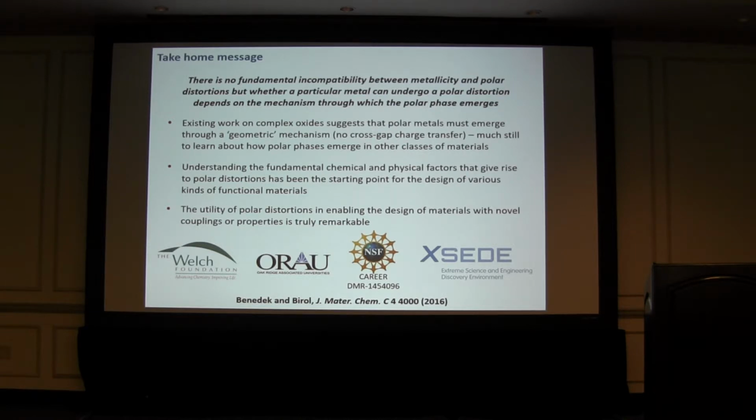I'm not convinced about your insistence on the fact that the Born effective charges contribute to the force constant, because they contribute only for longitudinal phonons, and here in the transition you are looking for a zero field transition. That is a transverse phonon, where the Born effective charge has no effect on that energy. So for trivial materials like sodium chloride, Born effective charges disappear. In this material there is a further phenomenon which could play a role, but I don't know whether it will be positive or negative.